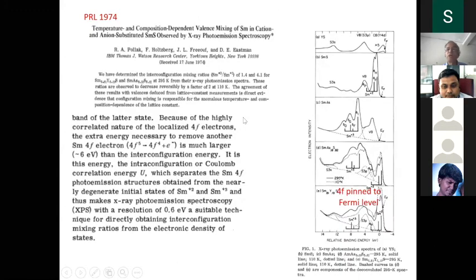Okay, now people did spectroscopy. People further proved this by electron spectroscopy measurements. This is the photoelectron spectroscopy here. You could see that if samarium is divalent, as in samarium sulfide at ambient pressure, these are typical fingerprints. These are the spectra you expect if you have a single valence state. If it is trivalent, as in samarium arsenide, you should get this kind of pattern.